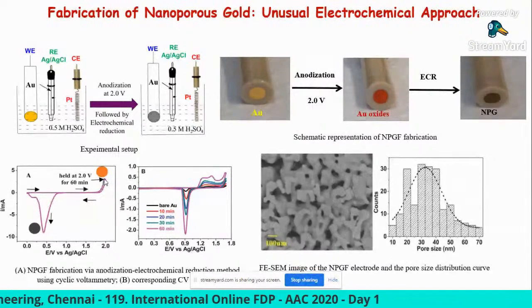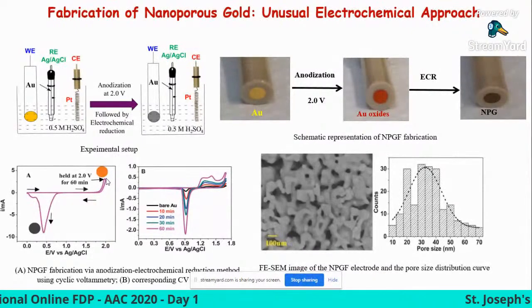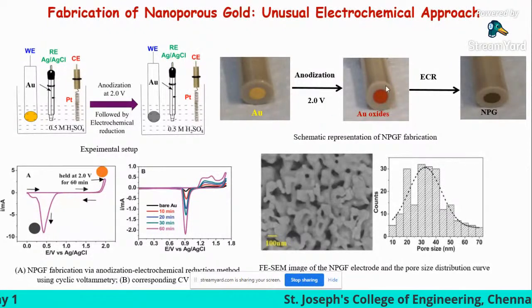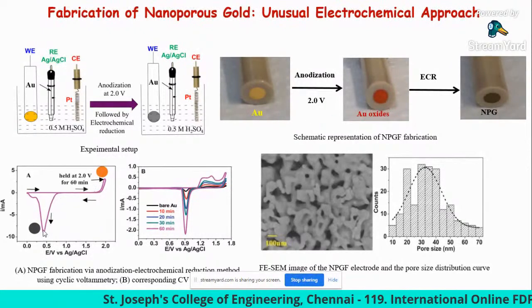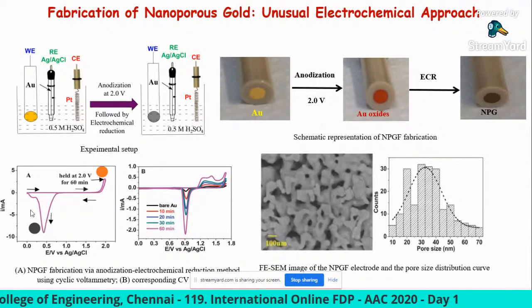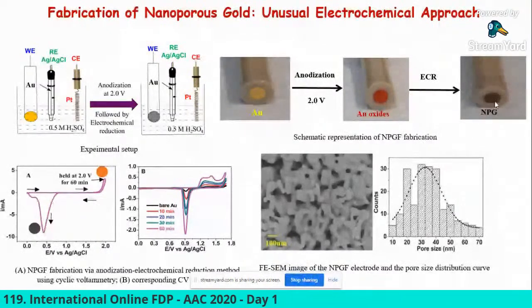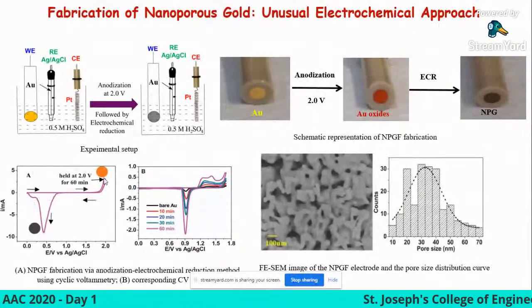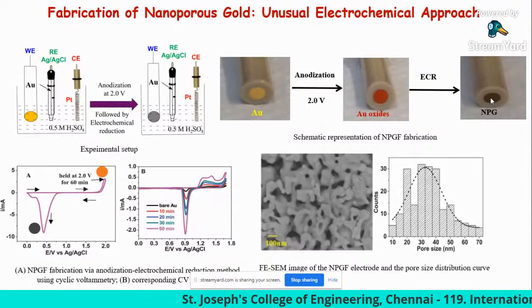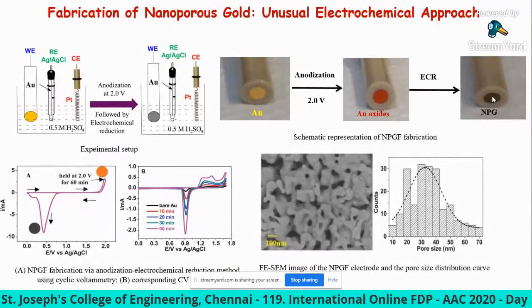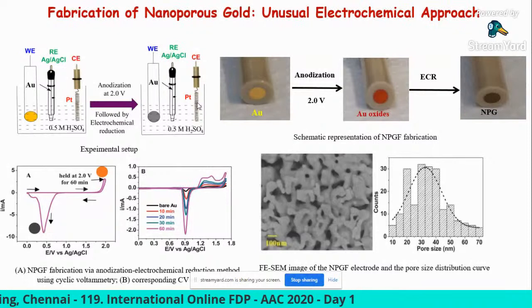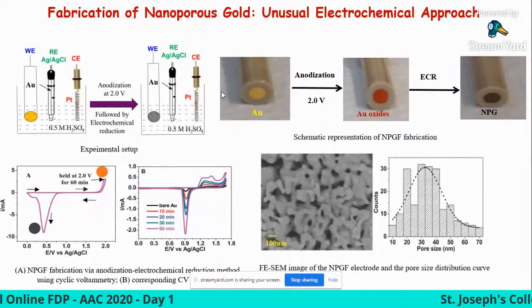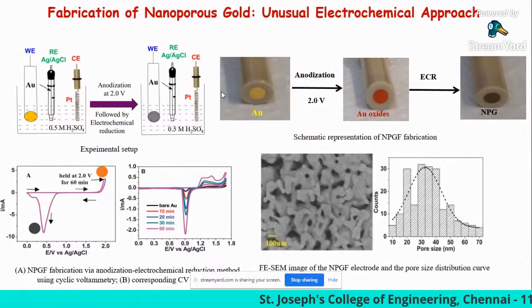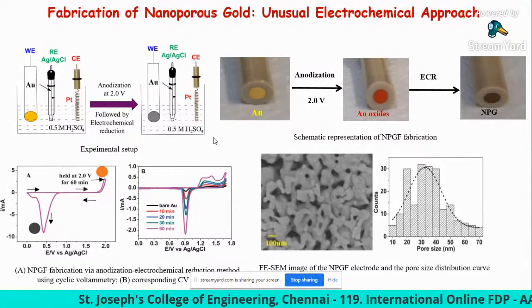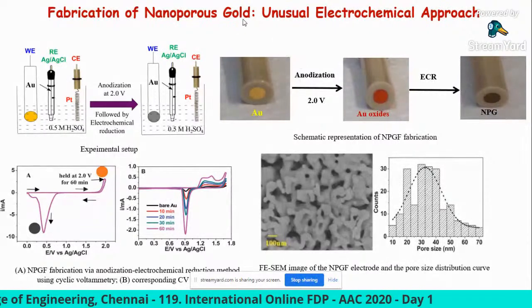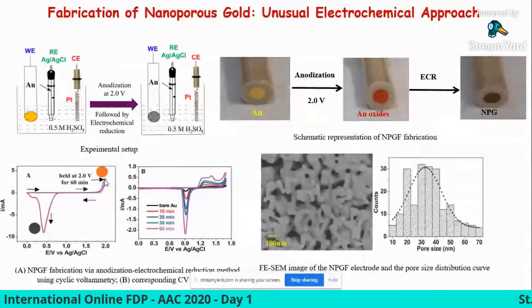Then after the anodization, we continue the cyclic voltammogram. The Au oxide formed is reduced in the reverse scan. During this reverse scan, the Au oxide is completely reduced to a nanoporous gold electrode. See, by recording a single cyclic voltammogram, we are able to get the nanoporous gold structure. In this process, we did not use a bimetallic alloy. We did not use any template. We did not use any reducing agent. So this is a very simple process we proposed for the fabrication of nanoporous gold, just by changing the electrochemical approach.